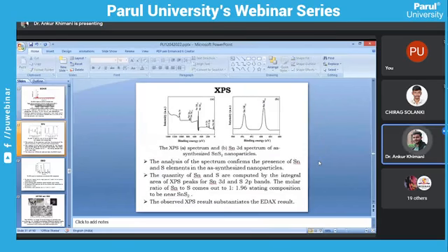Further chemical analysis is done by XPS. The intensity versus binding energy graph is given by XPS. So this is the zoomed graph, the intensity over the binding energy range of 500 to 480 electron volt. The analysis of the spectrum confirms the presence of Sn and S elements in the synthesized nanoparticle. The quantities of Sn and S are computed by the integral area of the XPS peaks for the Sn 3d and S 2p bands.